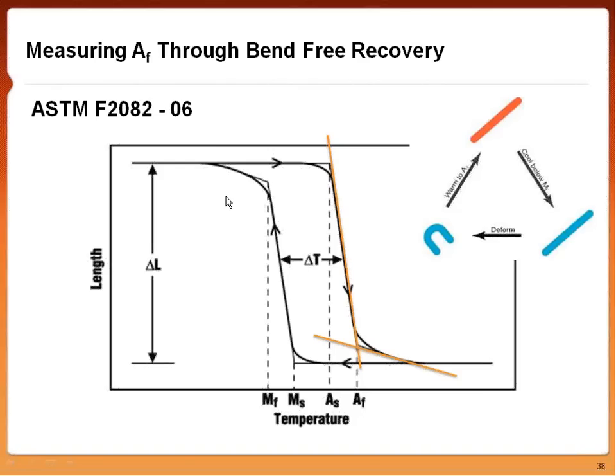When I talked before about the differential scanning calorimetry graph and the heat flow in and out of the material, it's really not good for testing the functionality of your device. When we test the functionality of the device, we look at the ASTM standard F2082-06, which says we need to do bend-free recovery of the nitinol material. Bend-free recovery is just using nitinol's shape memory aspect. You cool it, you let it deform, and then you heat it back up.